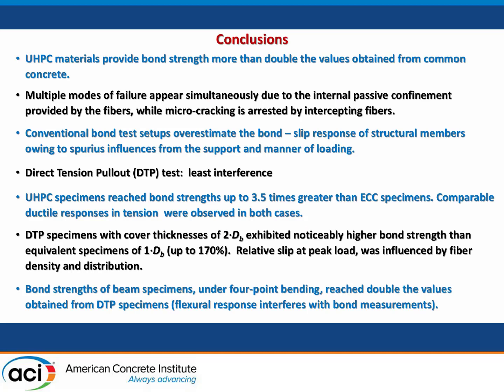So in conclusion, we find that the UHPC materials provide bond strength that is more than double the values obtained from common concrete. We saw multiple modes of failure appearing simultaneously due to the internal passive confinement provided by the fibers, while microcracking was arrested by the fibers that intercepted the crack path.